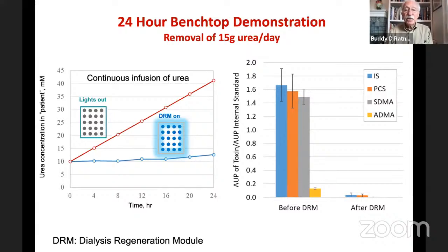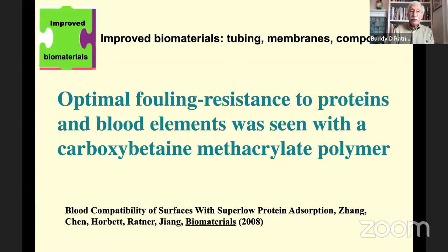Why? Because we're adding urea. When we turn the dialysis regeneration module lights on, see the blue curve, the urea concentration of the tank is remaining relatively quite steady. Again, that urea is being turned into nitrogen and CO2. On the right, we're looking at some of the other toxins that also have to be removed. And interestingly, this UV photocatalytic system pretty much burns up any organic, and so that has a number of advantages. We know for this whole system, that's how we're going to get rid of urea.